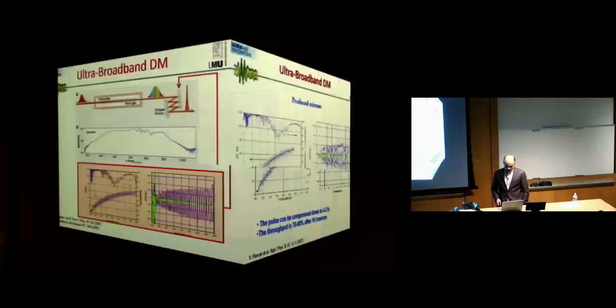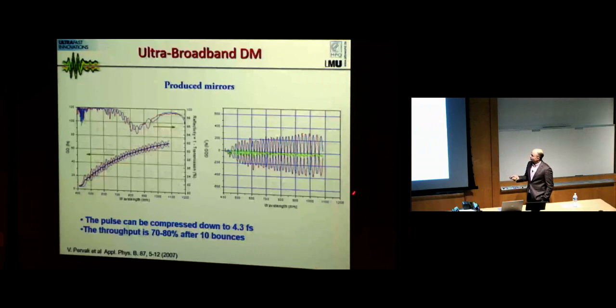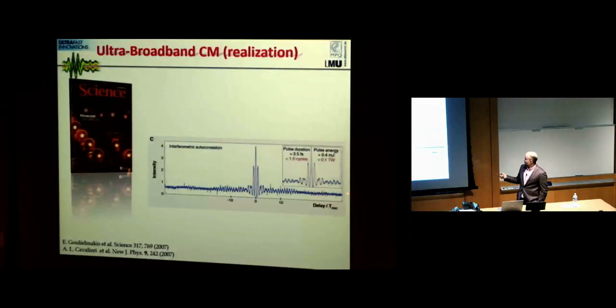Here we show how the mirrors look after production. Here is the GD curve, red and blue. It's for single mirrors, and with dark violet, it's a residual curve. Here it's the GDD curve for both mirrors. By applying these mirrors, we were able to achieve the throughput after 10 bounces, which was necessary to compress a pulse, 70-80%, to a pulse duration of about 4 femtoseconds. Here is how the autocorrelation function looks for this pulse.